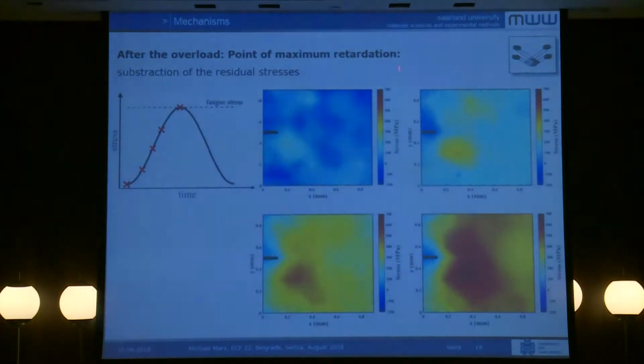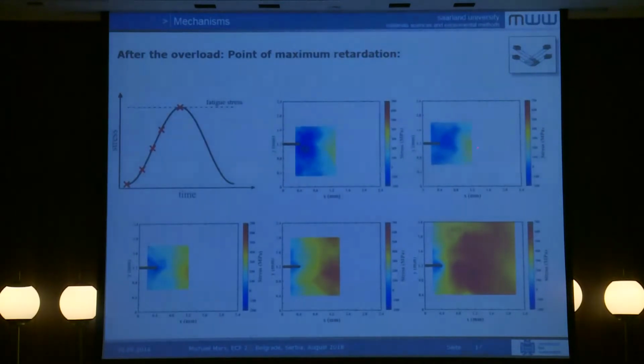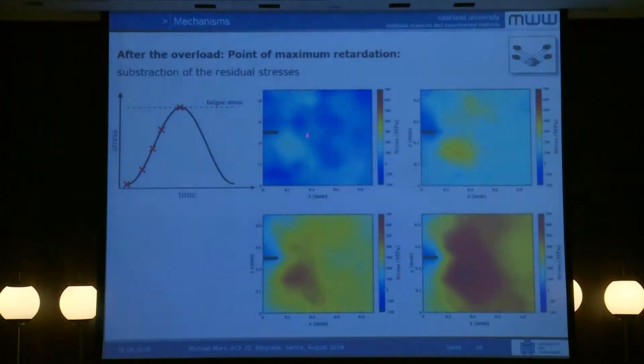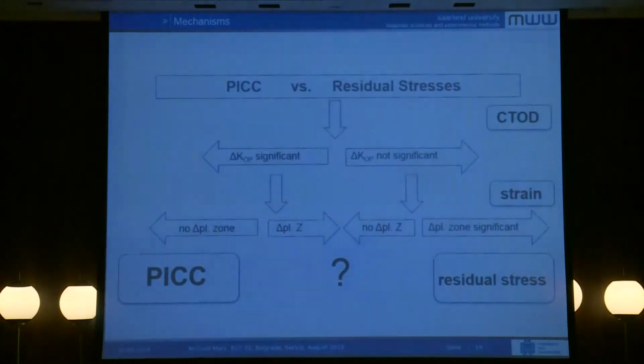And now you can also subtract the residual stresses from the applied stresses, which means the following images are these four images minus the values of this image. And then you see that at the beginning of your loading, you have some tensile stresses, but they are not working due to the compressive residual stresses in front.